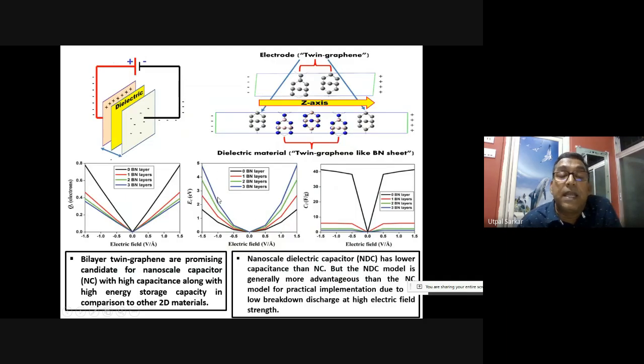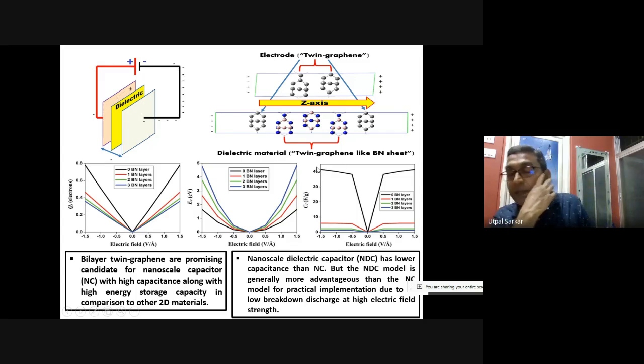This is the energy storage capacity. It is the 0 BN, no dielectric, and then we are increasing the layer one by one, and the highest energy storing capacity is observed for the 3 BN layer. Among these, capacitance is highest for 0, because at that time it is more polarizable, and if you put the dielectric, then it is less polarizable, and as a result you are getting less capacitance here.